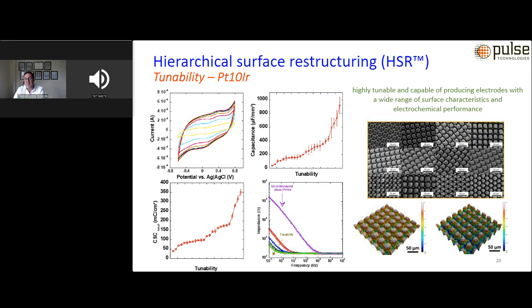So whether by adjusting and varying laser specific parameters such as laser average power, fluence, energy per pulse, repetition rate or frequency, beam size, spot size, or by varying lasering patterns on the surface, we have really an enormous number of ways in our toolbox to be able to tune the surface and control the electrochemical performance of the electrodes, which again makes the process very, very unique. And as you can see, a wide range of electrochemical performance metrics, such as charge storage capacity, specific capacitance, and impedance, are achievable with this process and the way it could tune the electrode surface and the electrode electrochemical performance.